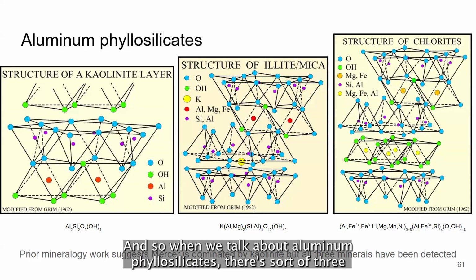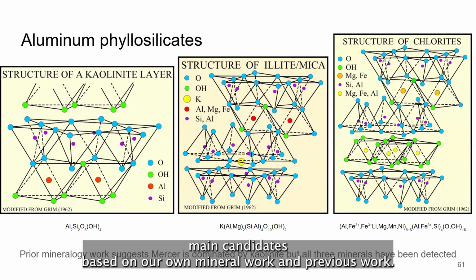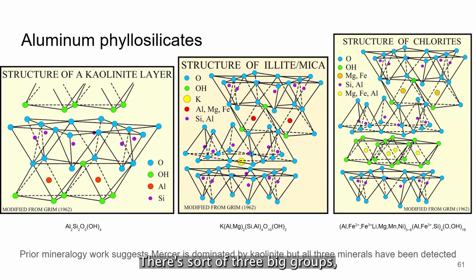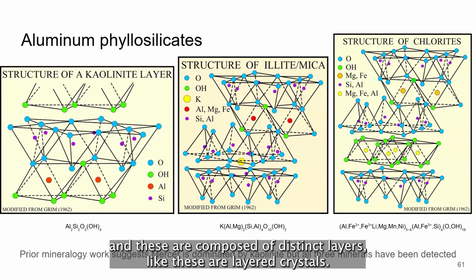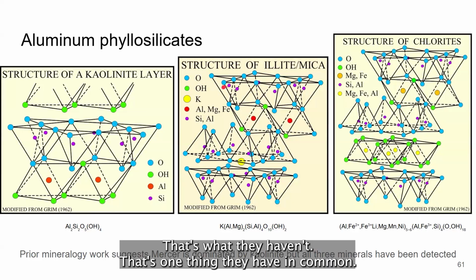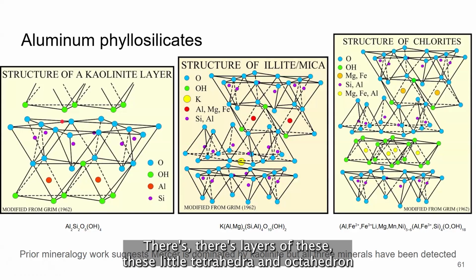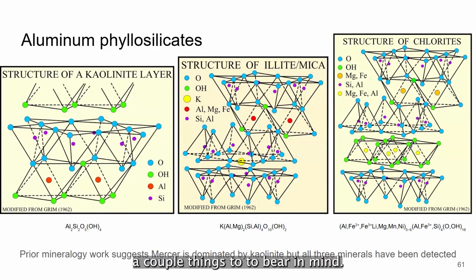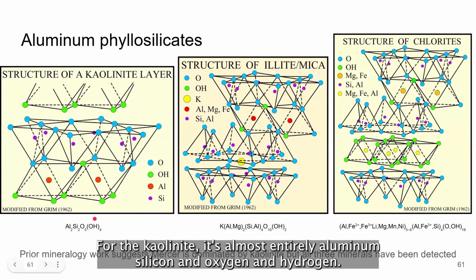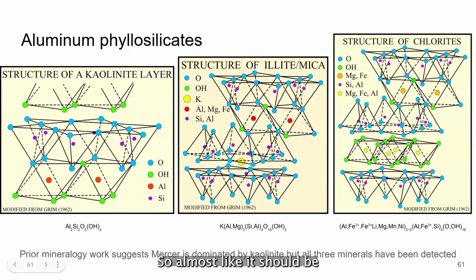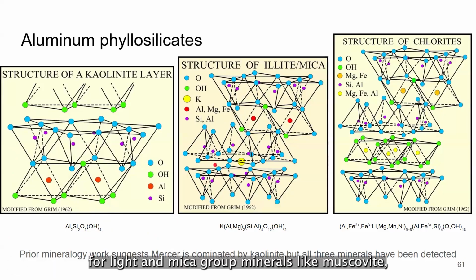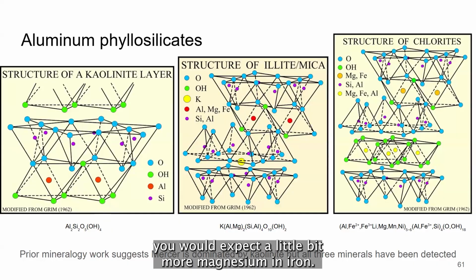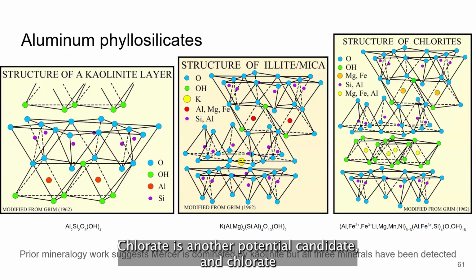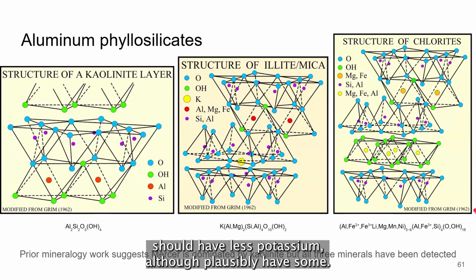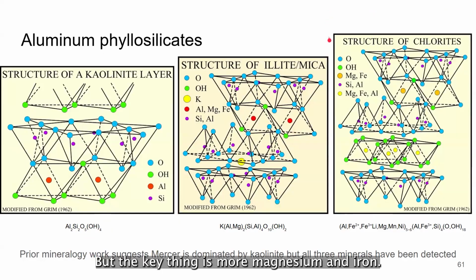And so when we talk about aluminum phyllosilicates, there are 3 main candidates, 3 big groups, based on our own mineral work and previous work. They're composed of distinct layers, layered crystals, with layers of little tetrahedra and octahedra stacked on top of each other. A couple of things to bear in mind. Kaolinite is almost entirely aluminum, silicon, oxygen and hydrogen, so it should be pretty close to pure aluminosilicate. For illite and mica group minerals like muscovite, you would expect a little more magnesium and iron, but the key thing is potassium. Chlorite is another potential candidate and should have less potassium, although plausibly some, but the key thing is more magnesium and iron.